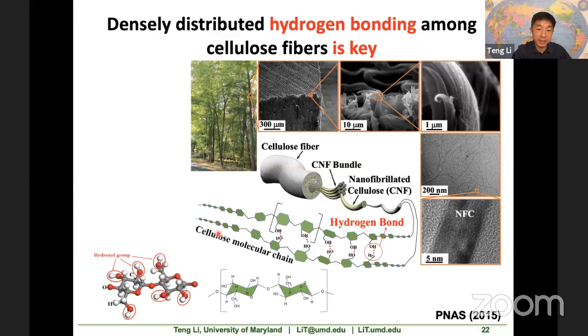As you can imagine, there are abundant hydroxyl groups on the surface of cellulose molecular chains. So when they are close by to each other, we know that the hydroxyl groups, when they're approaching each other, naturally form hydrogen bonds. Hydrogen bond is not a very strong bond in comparison with the ionic bond, the metallic bond, the covalent bond. However, they are easy to form.